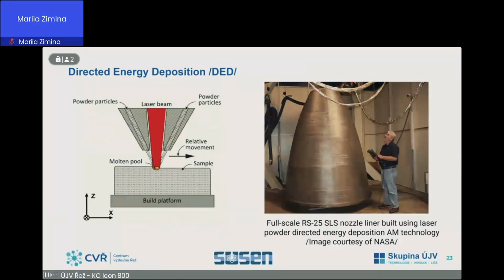Advantages of this technology are higher deposition rate, and it allows the production of larger components with mass up to 250 kilograms. Mechanical properties of such components, such as tensile, impact work, and hardness have been shown to meet or exceed the properties of the same type of material forged.